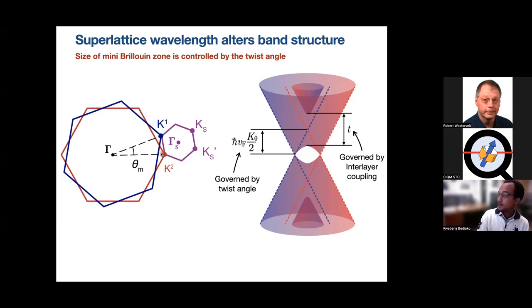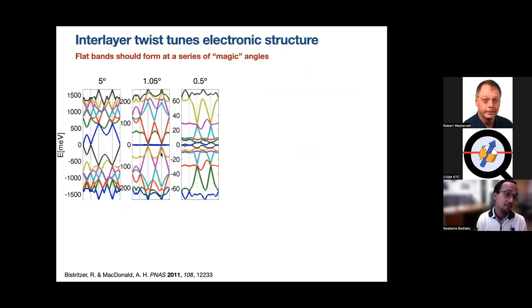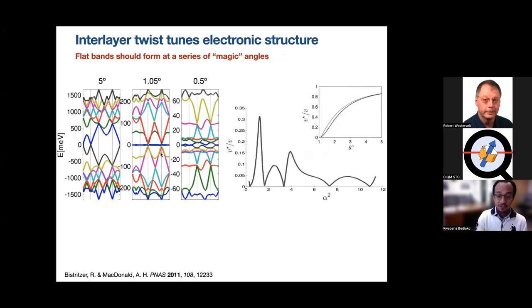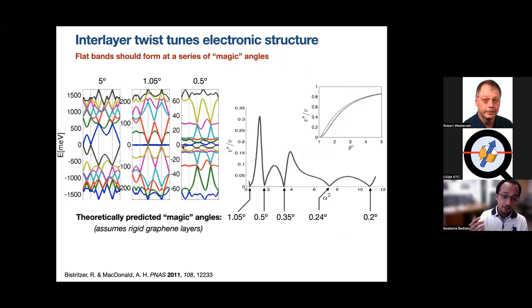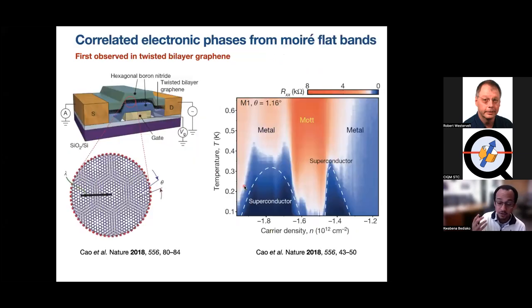the mini Brillouin zone. But when we consider all six, what you end up with is that theory predicts a series of magic angles, where the band structure of twisted bilayer graphene should display extremely flat electronic bands where the band velocity becomes vanishingly small. The first magic angle is about a degree, but a series of other angles are also anticipated or predicted. But importantly, these calculations assume a rigid graphene layer.